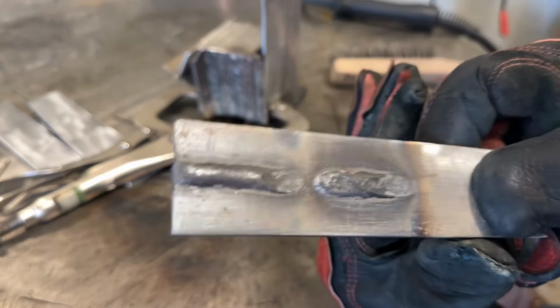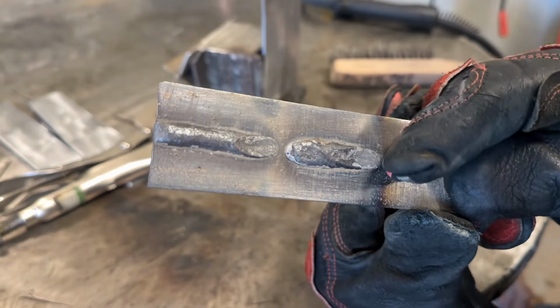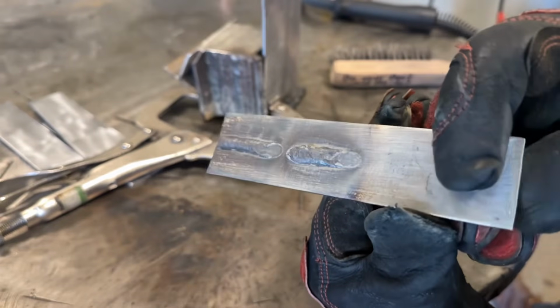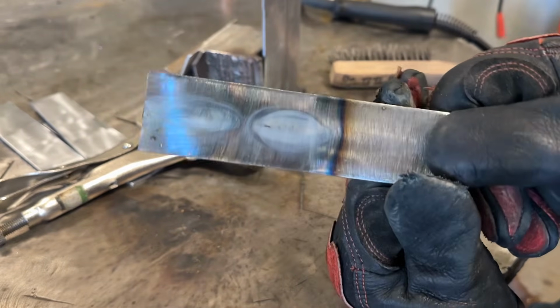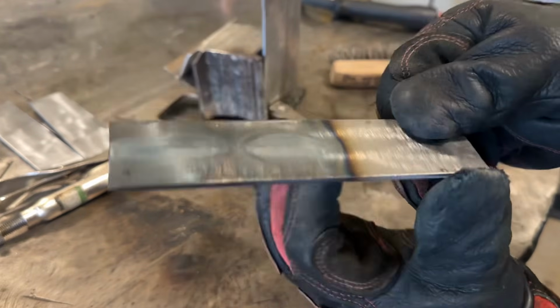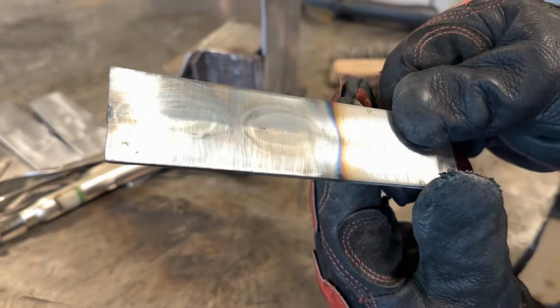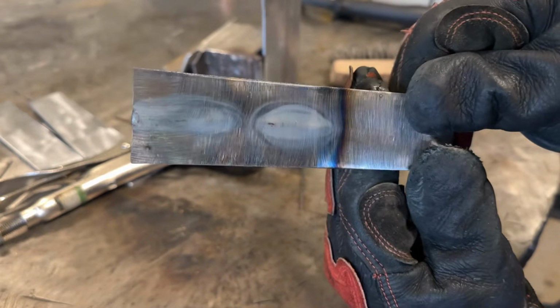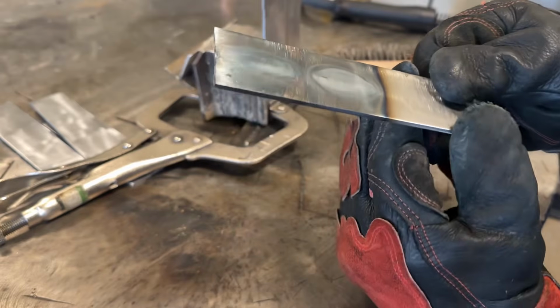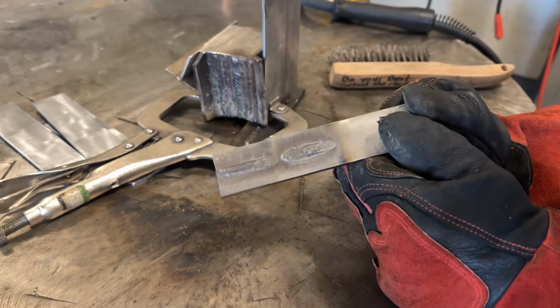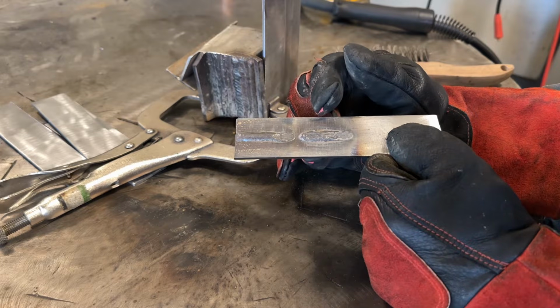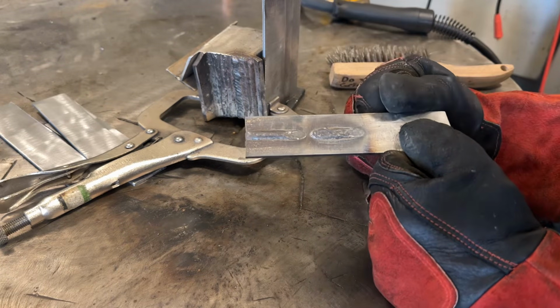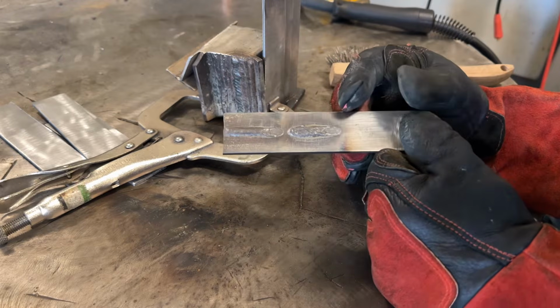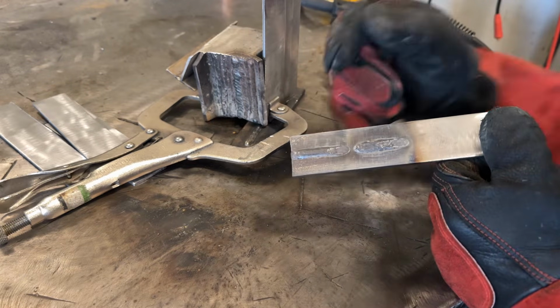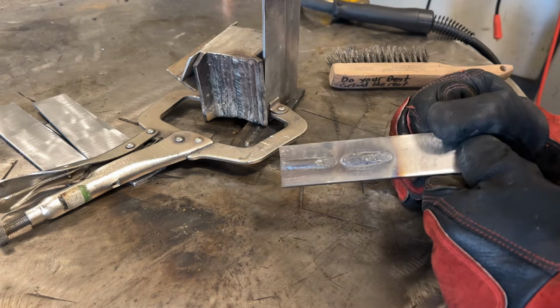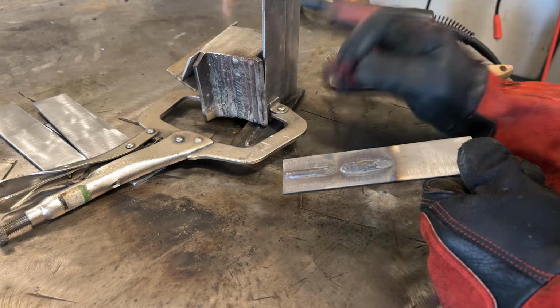So right away, and I didn't clean it that well, but you can see it's without question wider. It's rougher looking. The back side we see from this angle, I'll angle it. You can see how there's a really big crease there, much bigger than the first pass. Great indication, plenty of heat there. Like I said, that would be more or less acceptable for doing lap welds or fillet welds, but not in the uphill position. So you want your welds to look like this or slightly colder, and that will be the starting point to work with for doing uphill.